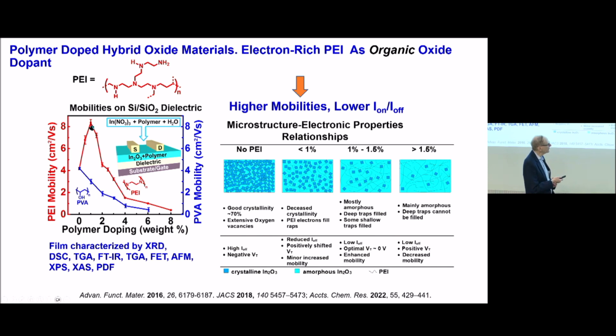And so we had the idea that let's do the combustion synthesis, but let's mix a polymer in. And this is PEI, which is very electron rich. So essentially it's going to dope the indium oxide. And just to sort of give you an idea, so as you add more and more of the polymer to the indium oxide and do the combustion synthesis. So we use indium nitrate. So that's part of the combustion. It's a strong oxidizing agent.